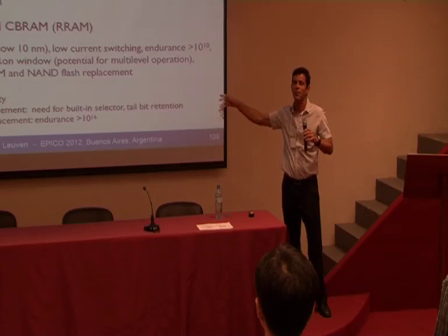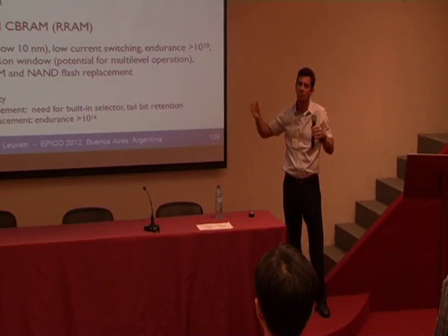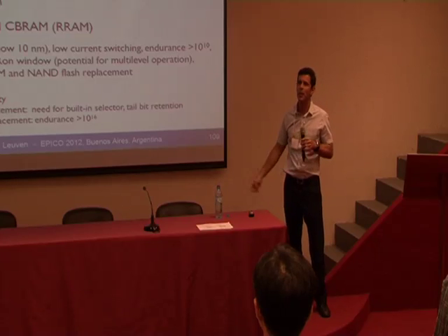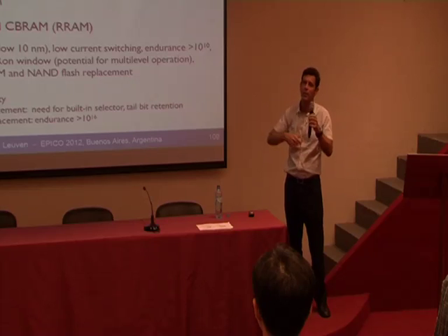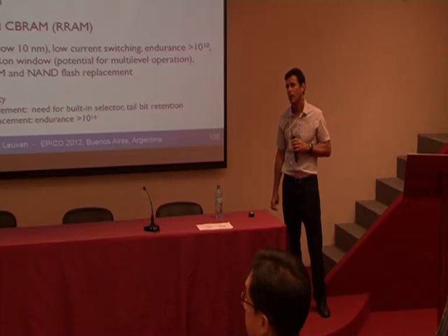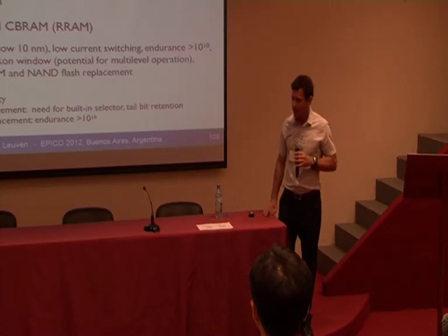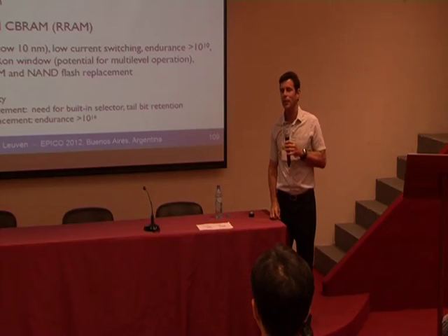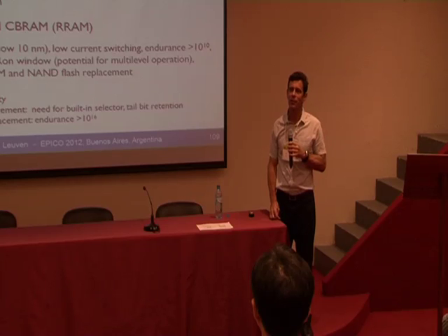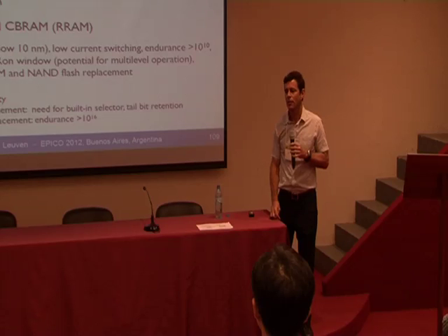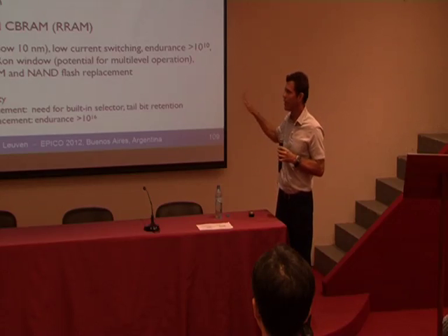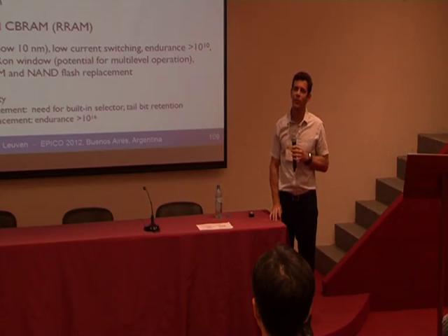I see. So if you do modeling of heat flow, you can more or less see what can happen and how and stuff like that. So it's geometry dependent, it depends on what you put below, on top, heat sinks, all this. And do you think this is true for all Mott resistors? Again, there are several papers in literature claiming exotic effects for the switching. We could explain everything with Joule heating. We didn't have to invoke other things.